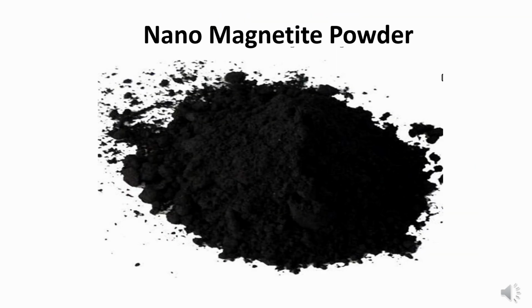When the black material was recovered and dried out, a very fine black powder was produced. Because it was attracted by a magnet, it was assumed to be ferromagnetic magnetite particles small enough to move freely in brine-filled, carbonate rock porosity. I had never encountered or even heard of this situation before in my 25 years in the oil patch.